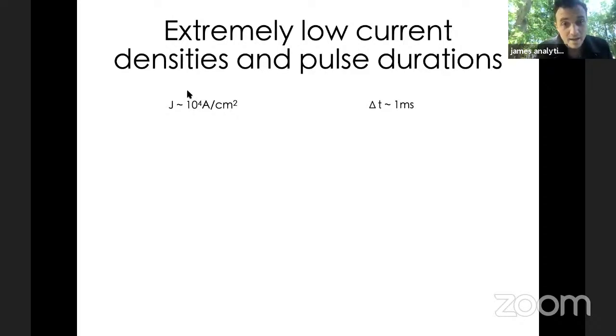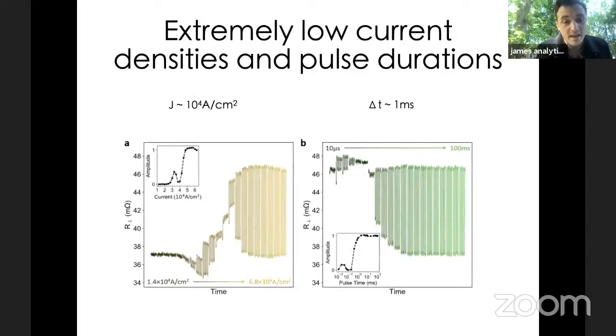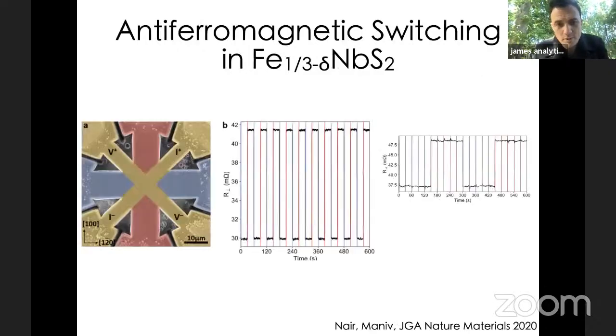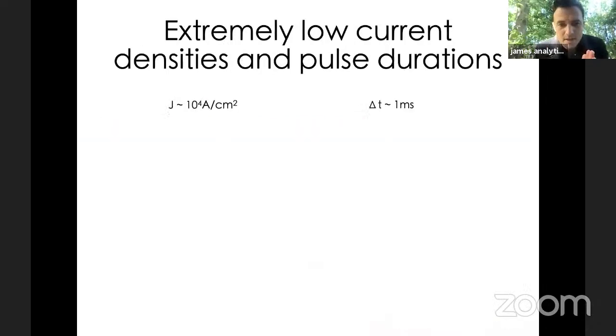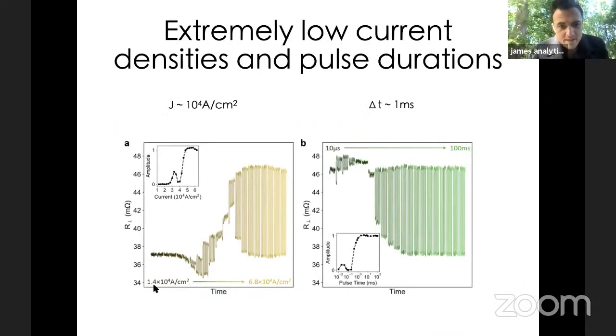The second part is that there's also a really non-monotonic current dependence. So here's the resistance change that you see. This is one of the pulse trains. What you're seeing here is just one of these pulse trains squished in for different current densities, and I have different current densities applied for each one of these pulse trains.